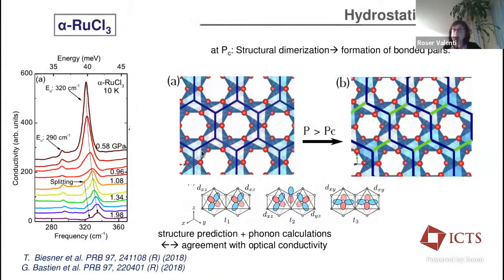So the first thing that you can think of is, if I want to change these interactions, let's apply pressure. So what happens, however, when you apply pressure? Here I'm showing conductivity experiments by Martin Dressel and collaborators, where they follow the phonons, especially this Eu phonon. What happens when you apply pressure, here I'm showing again these different hopping paths that are playing a role in the interactions, is that you're starting to make this interaction path the important one.